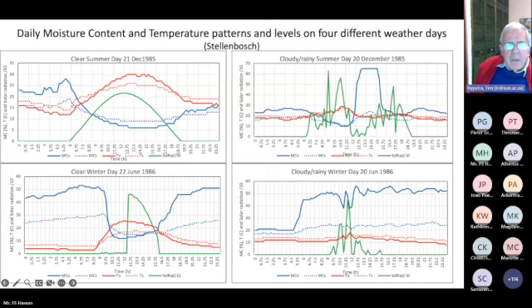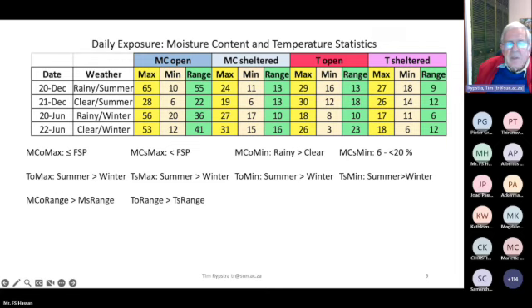Okay, next slide, please. So doing some statistics, and just taking out the maximum moisture content outside. Okay, that's a printing mistake. It is usually higher than the fiber saturation point. In other words, the maxima of 65, 28, 56, 53 are typical for wood that is fully exposed during these conditions, even when it wasn't raining, but still quite high, above say 30%, which is the fiber saturation point. And similarly with the sheltered condition, everything is more or less, except for the relatively high 31% for the clear winter day, 31% and less. In other words, below fiber saturation point.